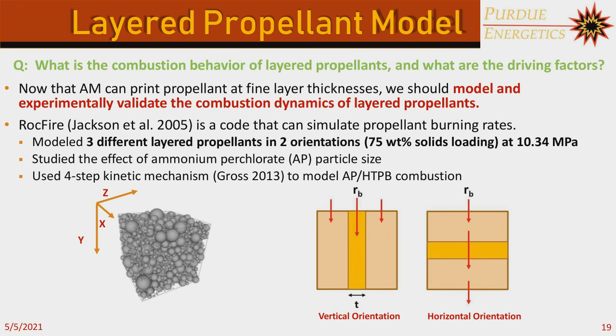For our particular study, though, we made layered propellants. So we did 3 different types of layered propellants. Essentially, the way we did that was we kept the outer layers the same. So those were supposed to be slow-burning propellants. And then the inner layer, we changed the particle size. We typically decrease the particle size in the inner layer so that it would potentially burn faster than the outer layers. So those are what the layer configurations look like.